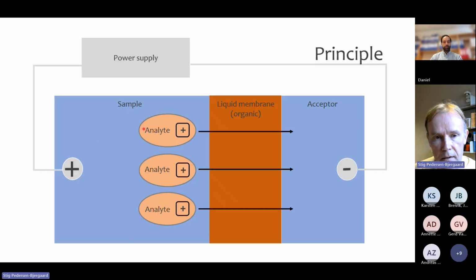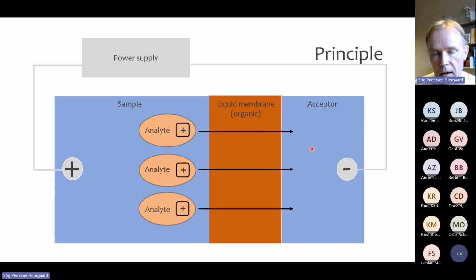So in EME, analytes of interest with charge, in this case positively charged substances in an aqueous sample, are brought in contact with a liquid membrane, which is a thin film of organic solvent. And on the other side of this organic liquid membrane, we have the acceptor solution. It is an aqueous buffer, and the extraction process is then driven by an electrical field sustained across the membrane, in this case with a negative electrode in the acceptor solution for extraction of positively charged analytes.